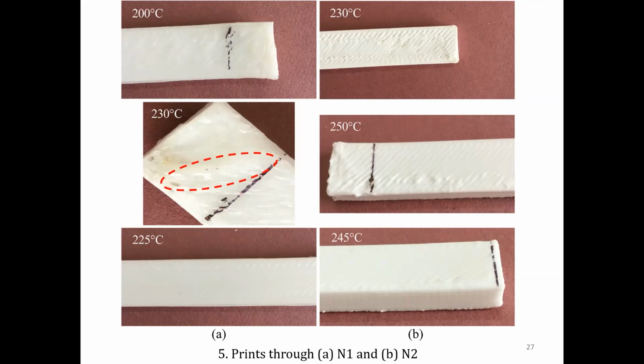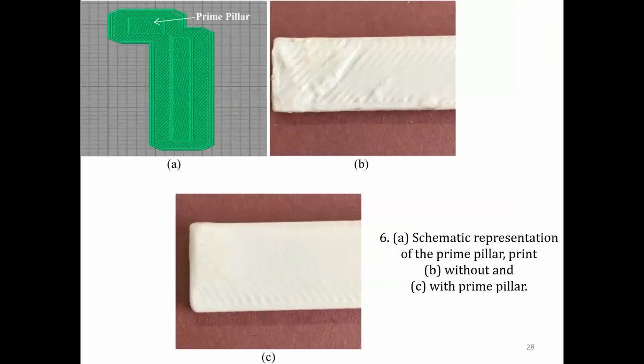Also, this is another term when you are operating fused filament fabrication. Typically, I have chosen fused filament fabrication even for today's presentation. The reason being, this is most probably available now in the tinkering lab, the product realization lab, where the first year students are trained in 3D printing. So there's another parameter known as extrusion multiplier, which is nothing but the volume of material flowing out of the nozzle. During our experiments, we were able to find the different numbers for different composites, which are readily available in our publications. And that is another parameter which we can always count on.